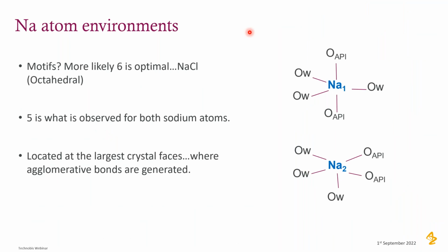The second thing we looked at is the sodium atom environment. The most likely optimal structure of sodium is, as we know from sodium chloride, octahedral. But in that crystal structure, both sodium atoms were only 5 times bonded. So you wonder if the sodium, because it is not completely optimally bonded, wants to bond with something else, a 6th friend, and therefore that phase becomes a bit more sticky. So that was potentially the initiation of an idea of what could happen at molecular level in the batch.